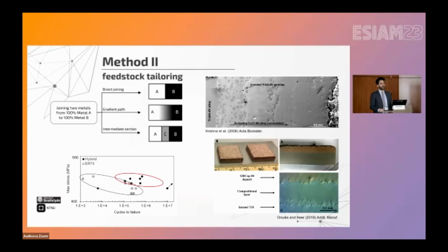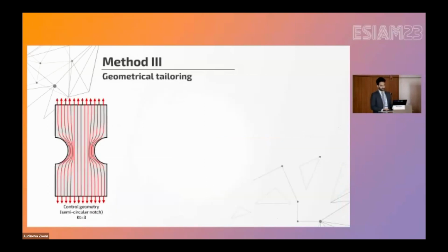We try to use a second material where we have the critical regions in the component. You can tailor it very simply, just a steel, and have high strength steel where you would like, and high ductility steel where you would like. And the process is being set with heated printing, so you don't need to do heat treatment afterwards. And the ultimate part that you can get can have favorable fatigue properties. This is a work we are performing with University of Strathclyde, and our preliminary data have shown an improvement in the fatigue performance of the parts. So this was quite short. Let's go to the third method to improve fatigue life.